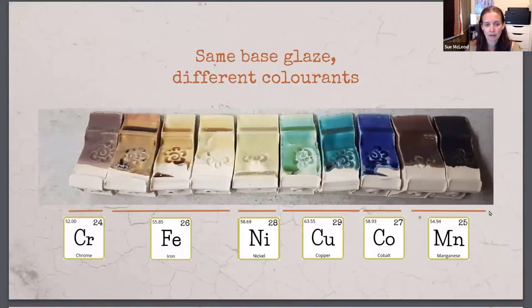So here's an example of this. These are all the same base glaze with different colorants added. So we've got chrome, iron, nickel, copper, cobalt, and manganese. So this is where we're changing the color. The base glaze stays the same, but we can add different colorants to the base glaze, and we can create a bunch of compatible glazes of different colors because they all have the same base glaze.